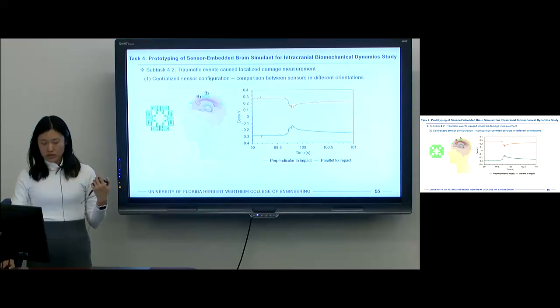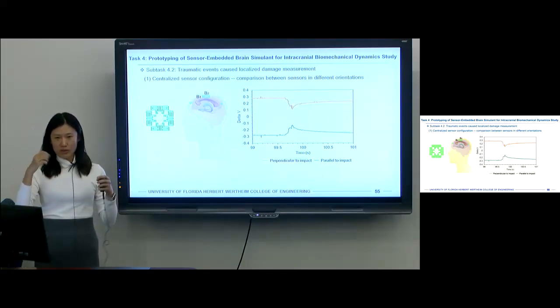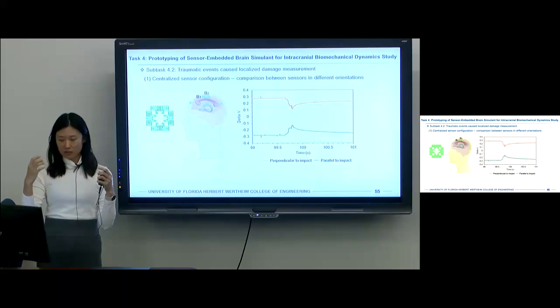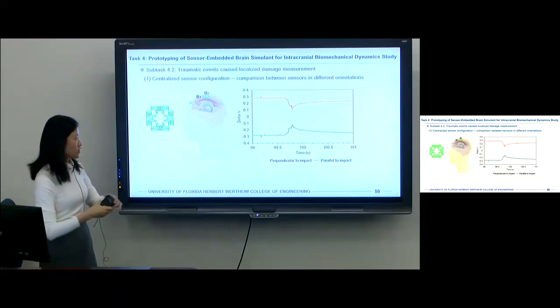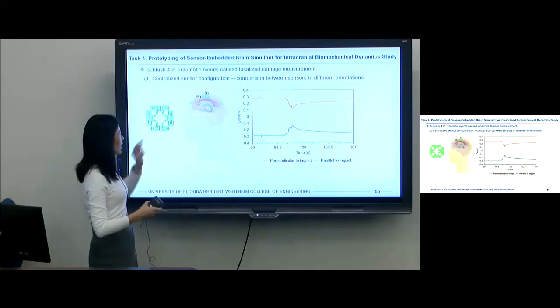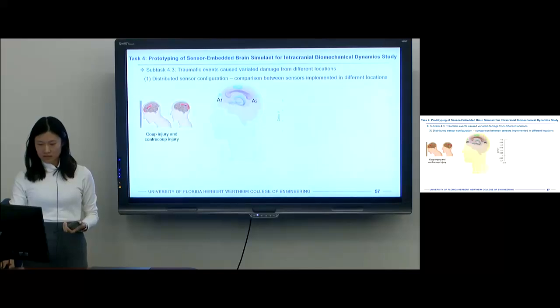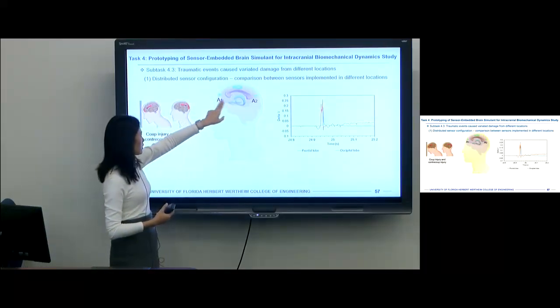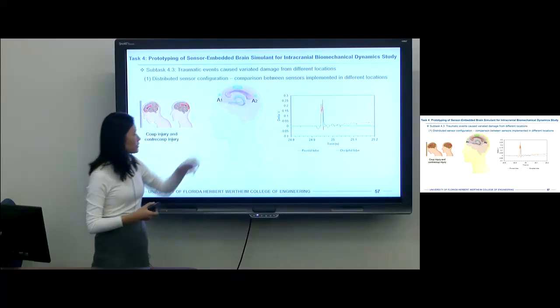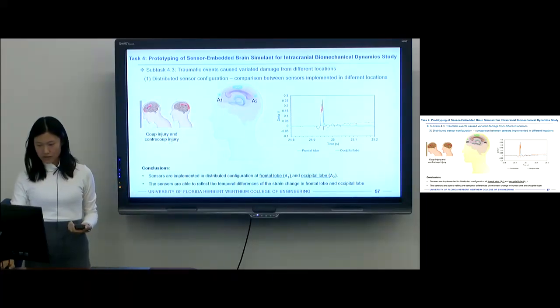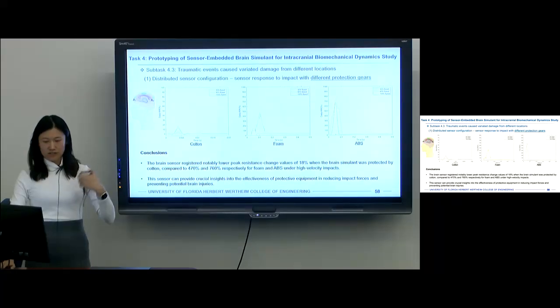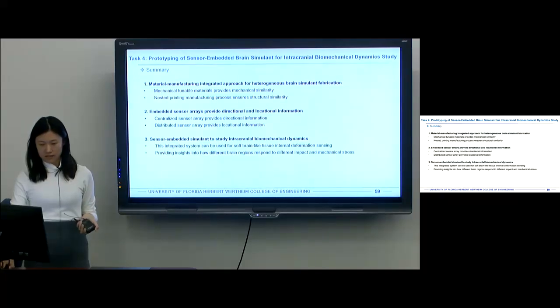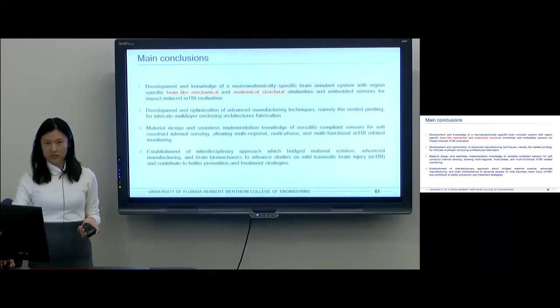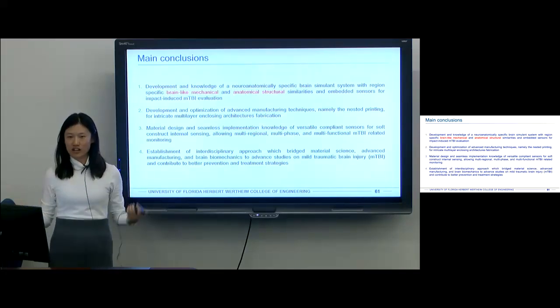We also tried the centralized sensor configuration. When we apply the impact from different directions, the sensors at different locations, for example B1 and B2, respond differently. For the distributed sensors, we applied them in the frontal lobe and occipital lobe, and we also observe different sensor deformation. With different protection gears, we also observe different responses. So I think that's the overall of this research.